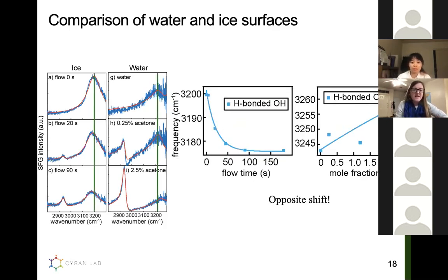Another thing you might not be able to see initially by eye from this data is that there are actually changes in the hydrogen bonded region for ice and water whenever we add acetone as well. So I drew a green line here to guide your eye to show you the shift in the spectrum. You can see that in terms of the ice data, we see a shift to lower frequency. And in terms of the water data, we see a shift to higher frequency. So what I did on the other side is I plotted this frequency shift versus the flow time or the mole fraction at this point.